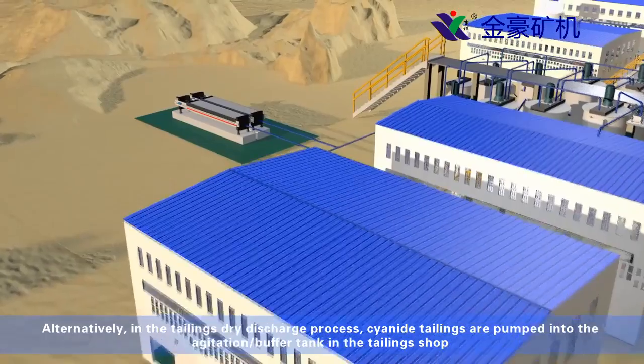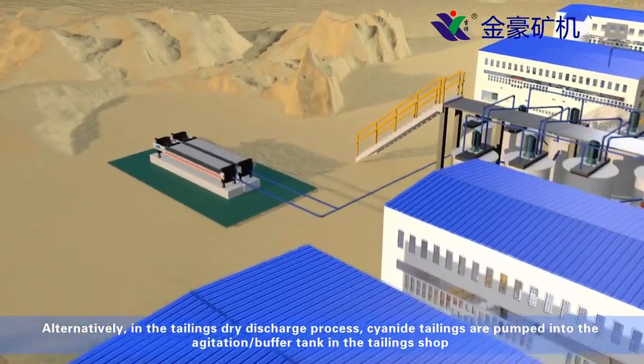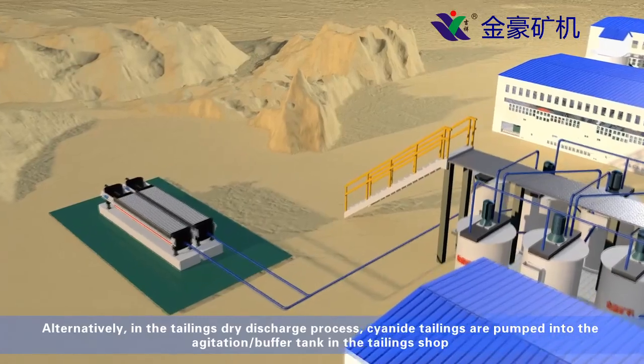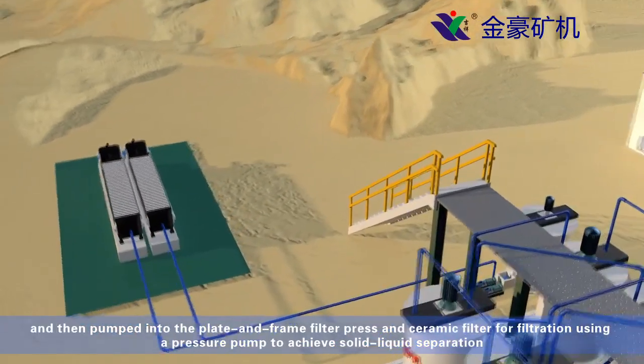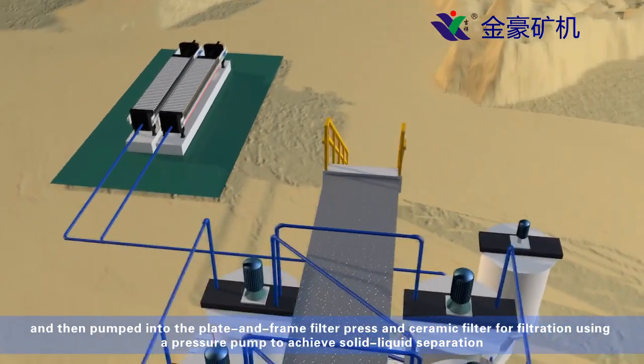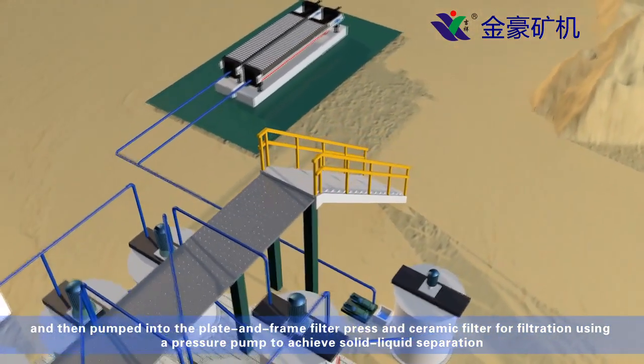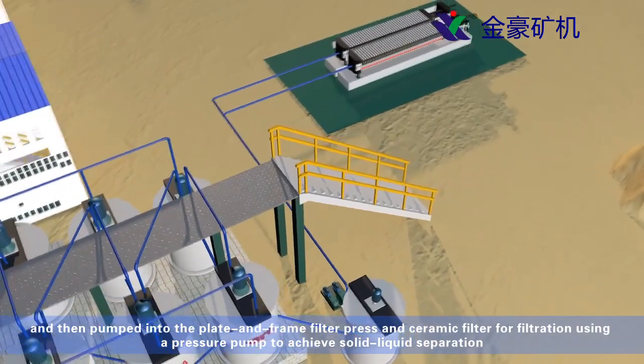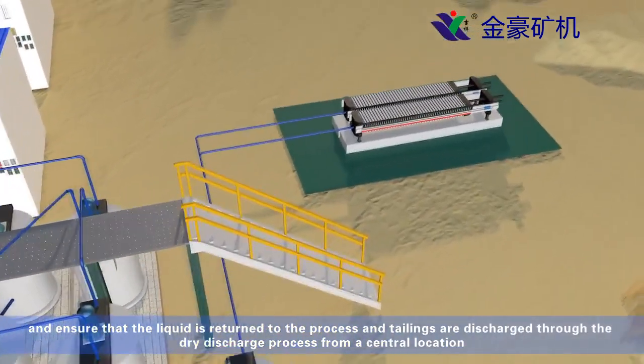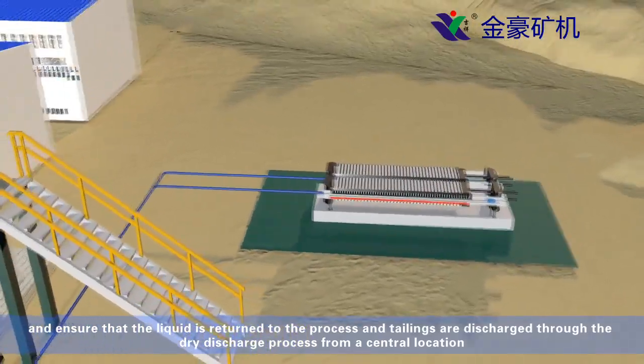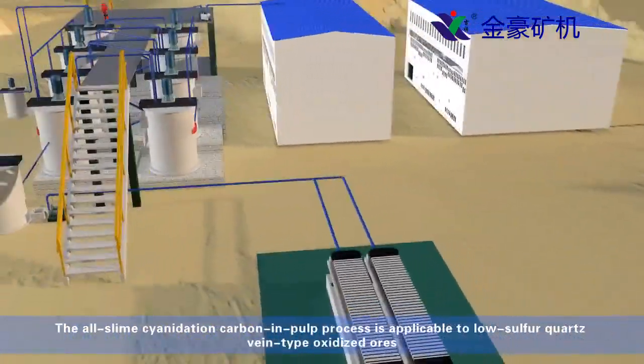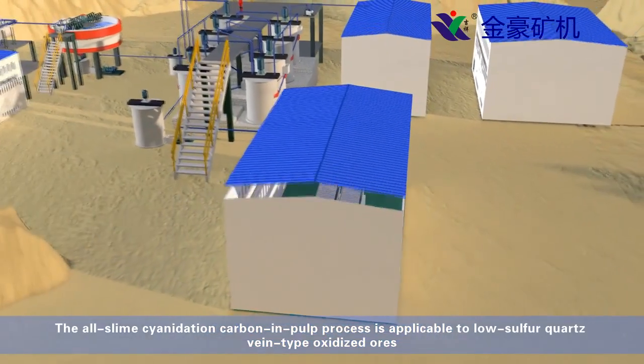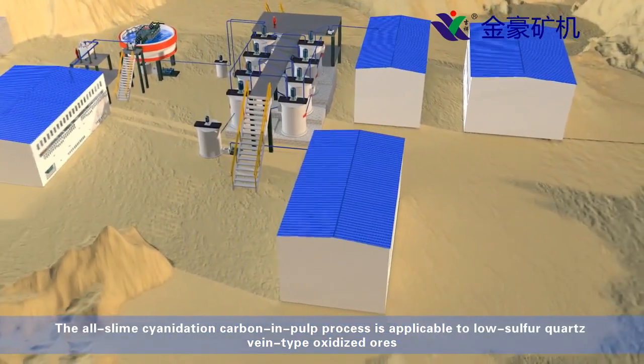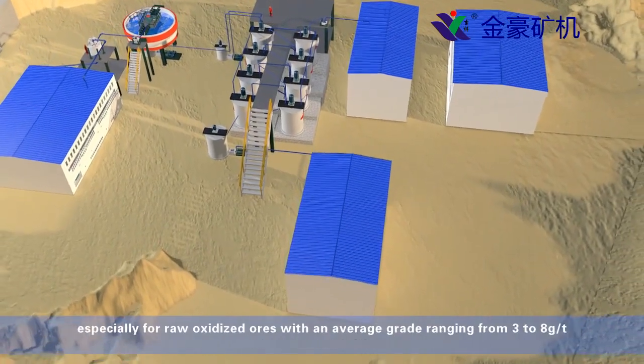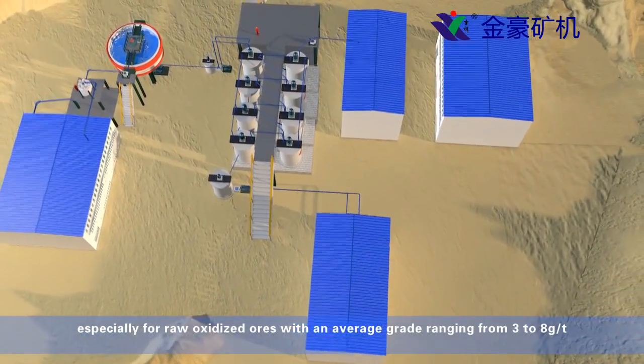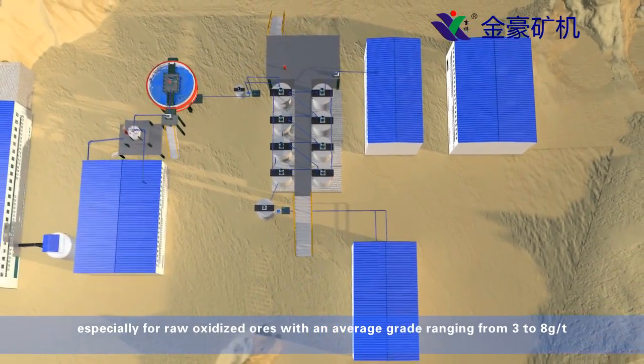Alternatively, in the tailings dry discharge process, cyanide tailings are pumped into the agitation buffer tank in the tailings shop, and then pumped into the plate and frame filter press and ceramic filter for filtration using a pressure pump to achieve solid-liquid separation and ensure that the liquid is returned to the process and tailings are discharged through the dry discharge process from a central location. The all-slime cyanidation carbon-in-pulp process is applicable to low-sulfur quartz vein-type oxidized ores, especially for raw oxidized ores, with an average grade ranging from 3 to 8 grams per ton.